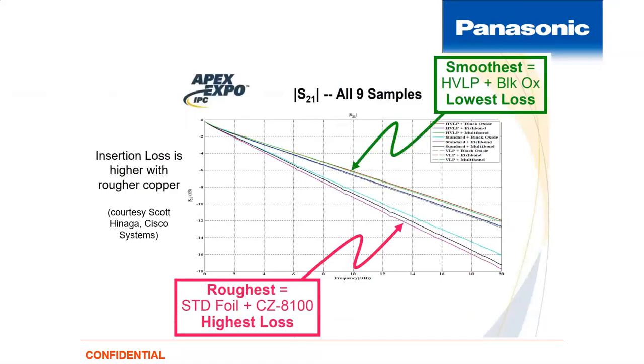And to show that, we could look at the dB loss graph again. Basically the upper side of this is the HVLP with black oxide, which gives the lowest loss, so the least amount of loss across here. And you can see the categories here are the numbers minus 14, minus 16, minus 18. Those are all higher loss values. So if we're looking at the HVLP, it's the least loss,